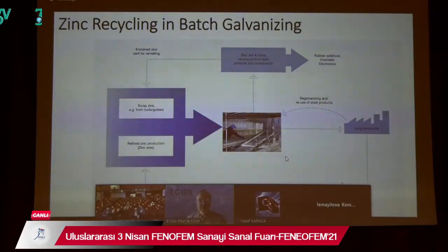At the end of life, we follow the other path. The zinc that may remain on the steel goes back into the steel recycling process. It emerges in the electric arc furnace dusts and finds its way back into the primary zinc production. So the zinc recycling circuit is a very strong one. It's very well established, and it's driven by economics. Zinc is a valuable metal, and it's therefore demanded by the recycling industry.